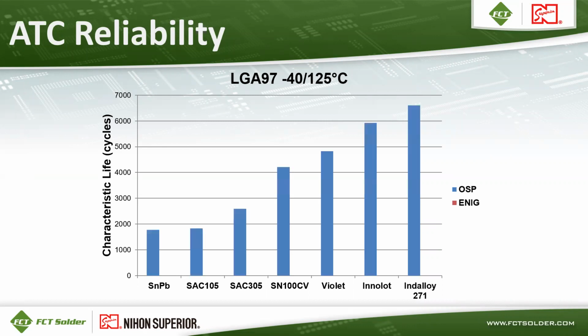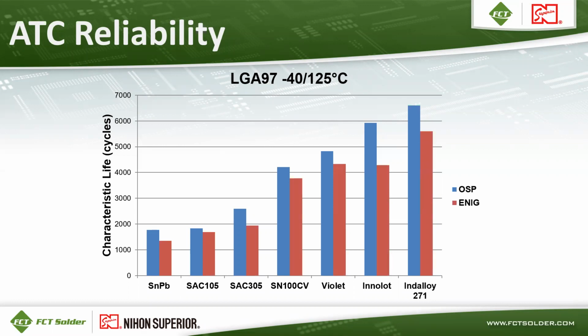Here's a chart of characteristic life for the LGA 97 for all those various alloys. And this is for the LGA 97 at a -40 to +125 temperature range. We've got two surface finishes that were tested, OSP, which are the blue bars. And you can see that characteristic life increases as you go from left to right on the chart. For tin lead and SAC 105, it's the lowest, and SAC 305 is relatively low. SN100CV, Violet, Innolot, and Indalloy 271 are all much higher in terms of characteristic life on OSP. That same trend is generally followed on the ENIG surface, although the lives are a little bit shorter on ENIG.